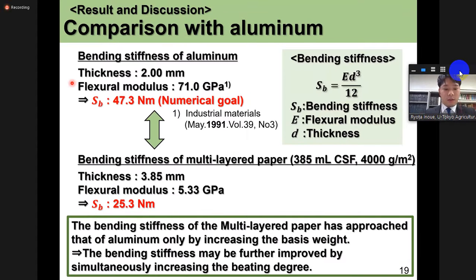In this slide, I'd like to talk about the comparison of strengths between multi-layered paper and aluminum for the new high volume applications from paper. We compared the strengths of the two materials by bending stiffness. Bending stiffness is calculated by multiplying the flexural modulus by the cube of the thickness and dividing by 12. Using this formula, the bending stiffness of 2 mm thickness aluminum is 47.3 Newton meters. We have set this value as a numerical goal.